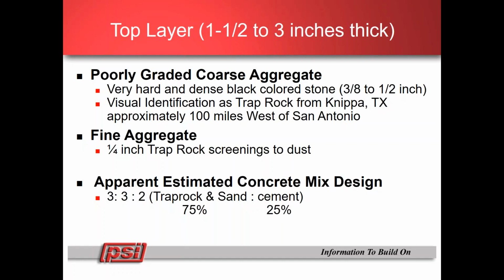The apparent estimated concrete mix had a composition of 3-3-2, or 3 parts trap rock, 3 parts sand, and 2 parts cementitious material. The cement was about 25%, and the trap rock and sand was about 75%. And visually, it's hard to separate the trap rock and the sand because we don't know whether that material was batched all together or whether the sand was added separately, and with the trap rock, how much of that fines were just part of the rock process.